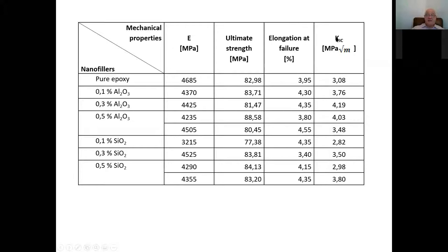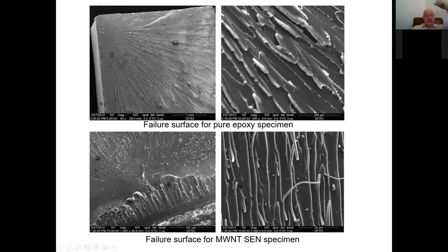Normally speaking, epoxy has a toughness of below 1 megapascal square root of meter. This is how it should be. So you want to increase toughness, but we feel that this increase of toughness is not correct. As you see, we got for pure epoxy 3.08, and this cannot be correct. So these results are under question. Of course, we are still planning to come back to this. I'm going to explain how.